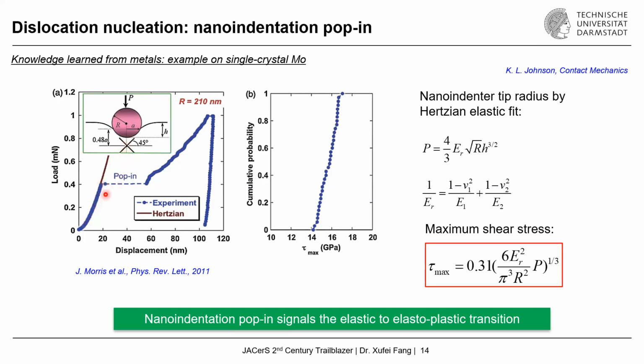And at the beginning, the material deforms elastically, and all of a sudden you see this so-called pop-in event, or the strain burst, as we call it in the nano-indentation community. And this is actually a signature of the elastic to elastoplastic deformation. And after that, the material starts to deform elastoplastically.